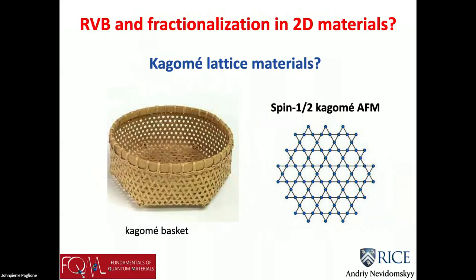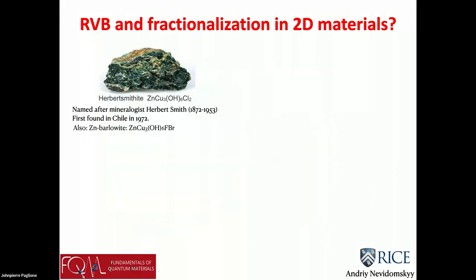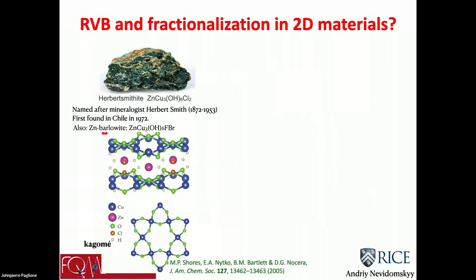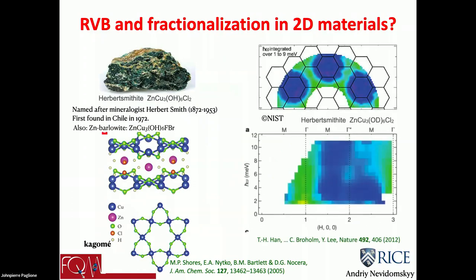The question, of course, is can you go beyond one dimension? I showed the example of the kagome lattice. There's a famous material called Herbertsmithite, named after a mineralogist, long after the mineralogist passed away. And it kind of looks like this. So essentially you have somewhat distorted kagome planes. The blue atoms are coppers, copper 2 plus, which as you probably know is spin half, just like in the cuprates. And the spin halves live on the vertices of the kagome lattice. If you do inelastic neutron scattering, what you see is the same continuum of excitations that was the smoking gun, quote unquote, in the previous slide, except now we're in two dimensions.